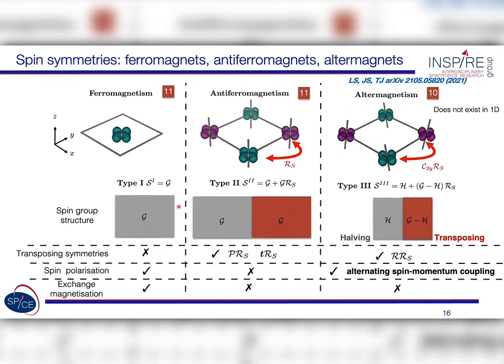These are the groups that have no transposing symmetries between the sublattices, and then you have exchange magnetization being present and a clear split of the bands. Whereas in the normal antiferromagnets, the spin reversal symmetry, RS, is a symmetry of your system. This also comes from the fact that you have a transposing symmetry between the sublattices, being a translation or parity. And naturally, of course, RS will be a symmetry of this type of linear antiferromagnets. On the other hand, if this spin flip is independent now of the spatial symmetry operations and comes only with a rotation symmetry,